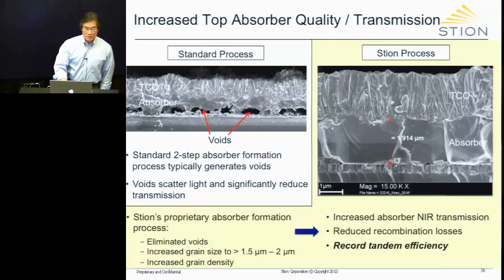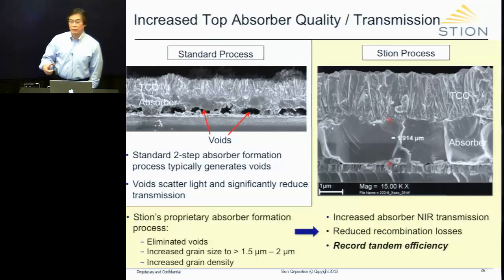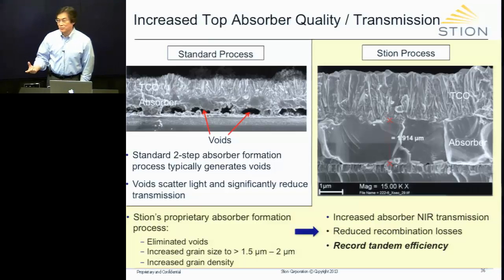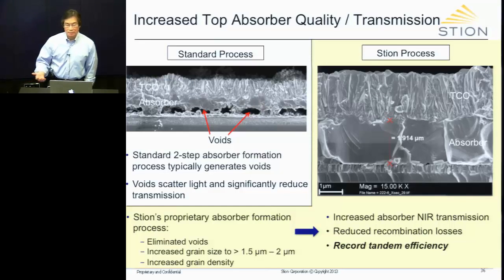Now, this is a single junction device on moly. So we don't have to transmit light. All right, this is the bottom device. So the voids don't matter to us. What really matters is whether the efficiency can be very high with those voids. It turns out you can. The efficiency can be extremely high, even with voids there. What's the disadvantage of the voids? It's the delamination that can occur. So it's a right balance between efficiency and the delamination issue.